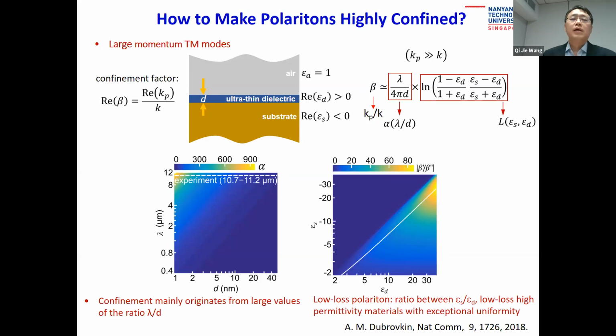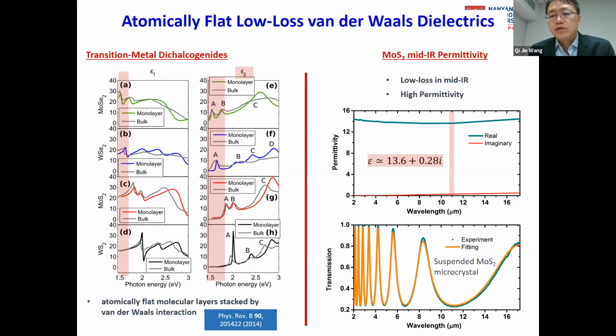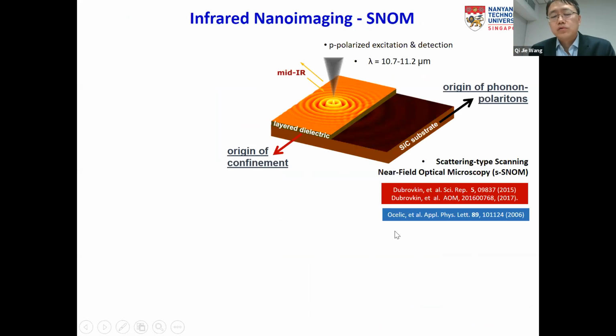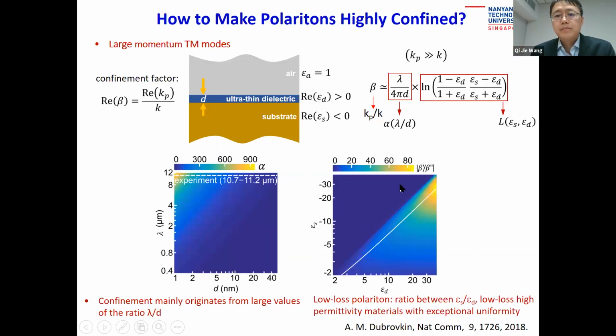In terms of high performance, I won't say that such a system provides extremely low loss or extremely long propagation length. That's not exactly true, because these 2D materials still have some loss, as I show in this characterization, in this measurement, right? And of course, the additive effect and the scattering all happen. But the main thing I want to show here is the high confinement property by using 2D material. That's the unique thing. Other materials, other than 2D materials, cannot be used to implement such a property because of a fabrication challenge. You cannot fabricate such a thin layer on the polar substrate.